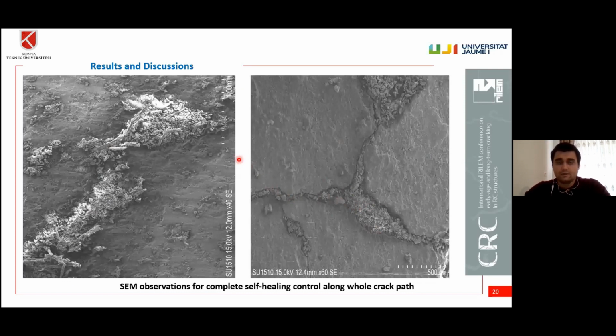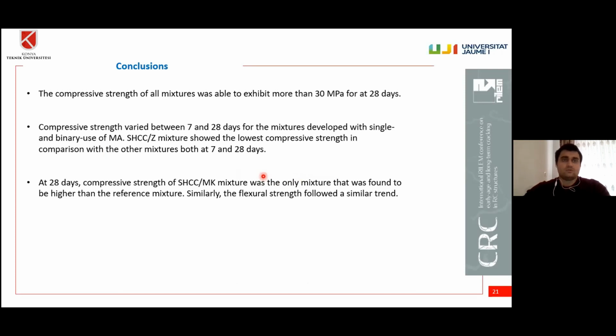Now, in future studies, we will also characterize the self-healing products based on different mixtures, and we will also evaluate mechanical recoveries like ductility, which is very important. To conclude, the compressive strength of all mixtures exceeded 30 megapascal at 28 days. We can consider this value applicable for general purpose construction sites. Of course, the compressive strength varied between 7 and 28 days because of the mineral admixtures. The zeolite bearing mixture showed the lowest compressive strength in comparison with the other mixtures, at both 7 and 28 days. Also, at 28 days, the compressive strength of metakaolin bearing specimens was the only one found to be higher than the reference mixture, and this result was also valid for the flexural strength.